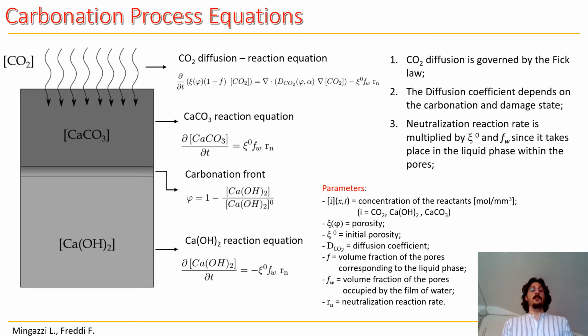For the reaction part, the reaction rate is multiplied by the porosity and the volume fraction of the pores partially occupied by water, because it represents the actual condition in which the neutralization reaction takes place. For the calcium carbonate and for the calcium hydroxide, we have only the reaction term. For the calcium carbonate, it accounts for the formation of the new material, while for the calcium hydroxide, it accounts for its consumption during the reaction.